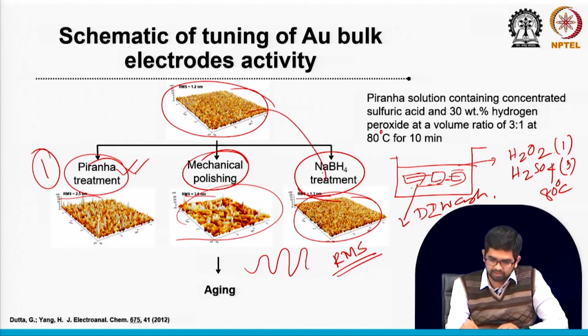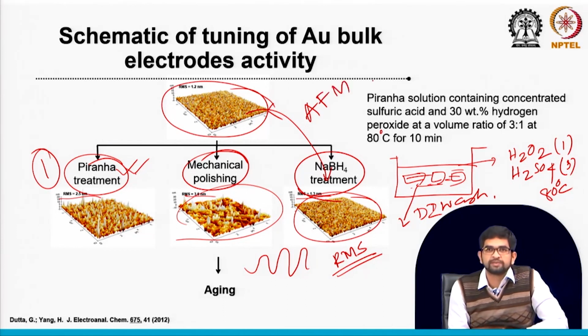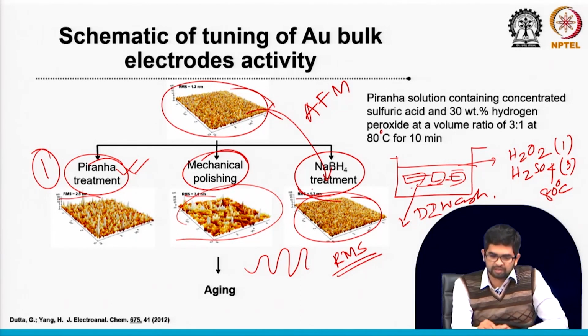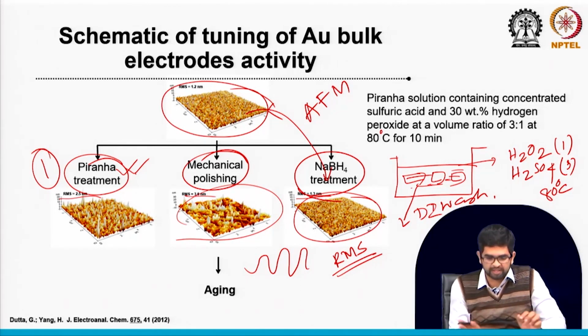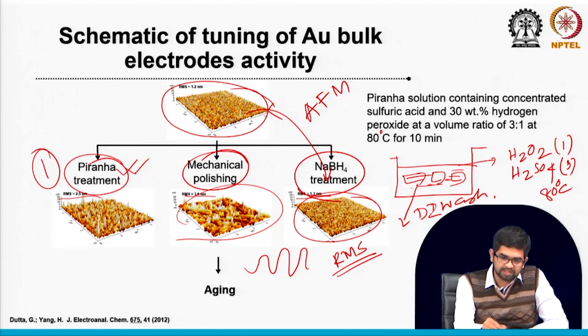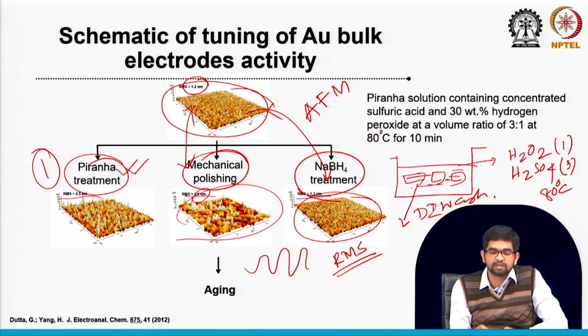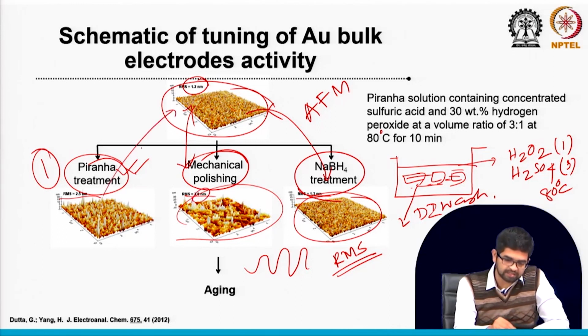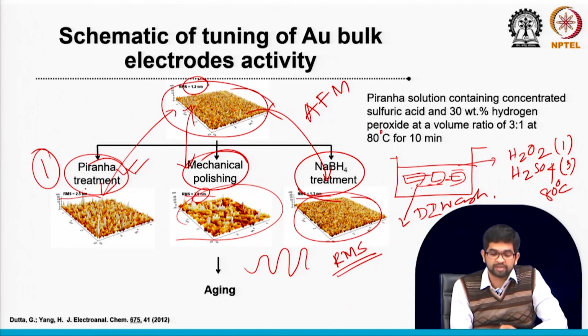See, for the sodium borohydride case, this is the AFM, atomic force micrograph image. See, in this case the roughness is almost similar. 1.2, 1.3 means we are saying almost similar, there is no change. But you can see here 1.2 nanometer before treatment, but in the mechanical polishing case the roughness changes to 3.6 nanometer, and in the piranha case it changes to around 2.5 nanometer, and it becomes a little rough surface.